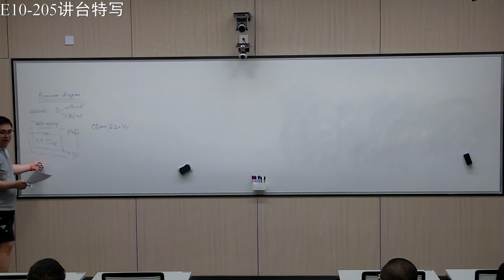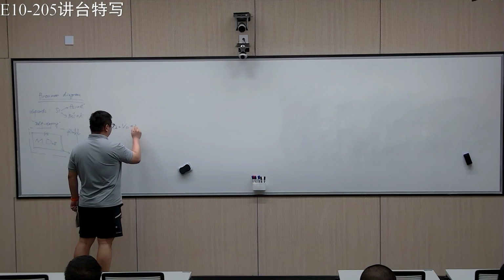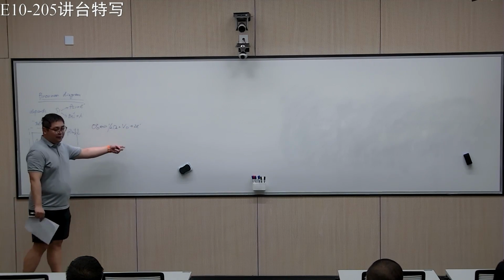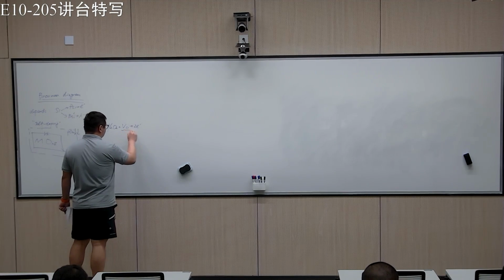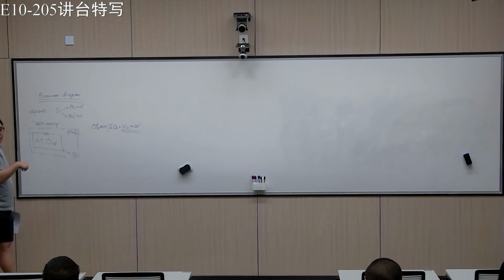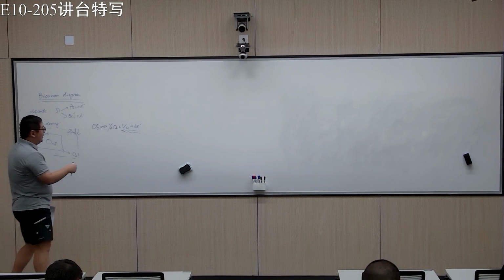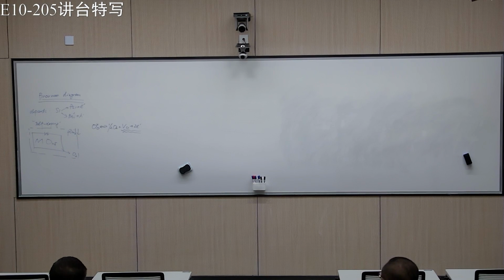However, the sample has to be charge neutral. The bulk of the sample, or of any crystal or ceramic, has to be charge neutral. So you have to balance the charge, and the way to balance the charge is that you have two electrons. Now this is similar to the case of the donor dopant. Essentially, you change the surrounding environment to create oxygen vacancies, and you create electrons. You put electrons into the system.